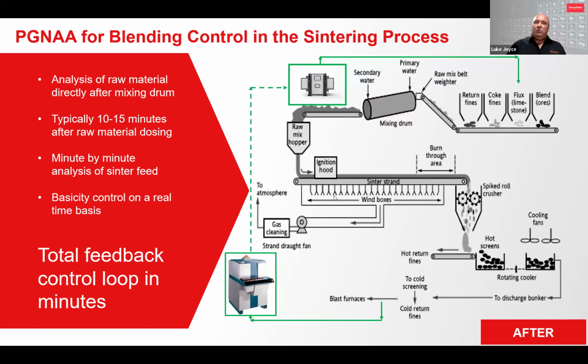I can see parallels with other smelting applications, an example being copper. Direct measurement of sulfur, iron, and copper can enable blending control of the concentrates, and also measurement of the silica can be used to directly control the silica addition to achieve a consistent iron-silica ratio.